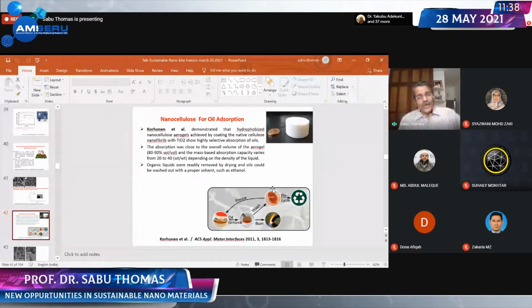Now let me show you the work of Korhonen and group from Finland, Scandinavia. They did some very interesting work. You know what they did? Look at this picture. They made aerogel out of nanocellulose. That's a very simple process. You disperse nanocellulose in water and go for a freeze-drying process. And if you do that, you get beautiful aerogel.